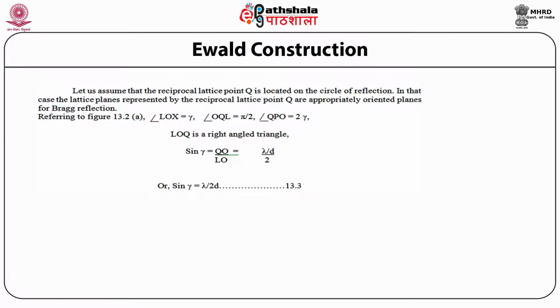Let us assume that the reciprocal lattice point Q is located on the circle of reflection. In that case, the lattice planes represented by the reciprocal lattice point Q are appropriately oriented planes for Bragg reflection. Referring to figure 13.2a, angle LOX is equal to gamma, angle OQL is equal to pi by 2, angle QPO is equal to 2 gamma. So LOQ is a right-angled triangle. Therefore, sine gamma is equal to QO upon LO is equal to lambda by d upon 2, or sine gamma is equal to lambda by 2d, which is given as equation 13.3.